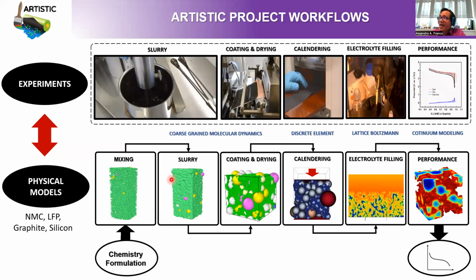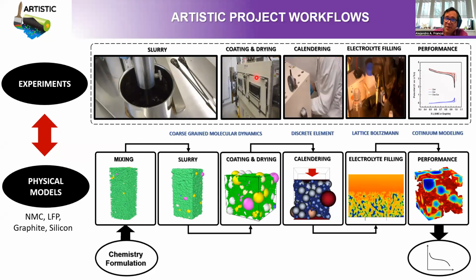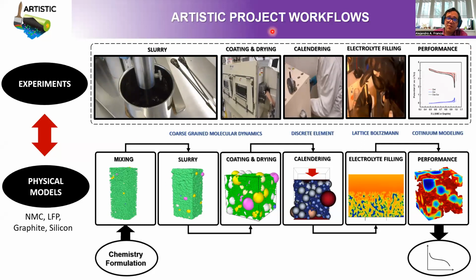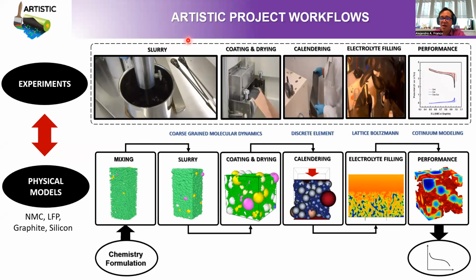So first of all, this is a recap of this ARTISTIC project workflow. So we have on one side experiments going on in our prototyping line, where we perform fabrication of slurries, coating, drying, calendering, and so on and so forth. And then we have all these physics-based models which are sequentially linked. We simulate the mixing, which is something that I didn't talk about today because the paper is still not written, right? Then the output of mixing goes into the slurry model. The slurry output goes into the coating drying model. Then the output of this model goes as an input of the calendering model. The output of the calendering goes into the electrolyte model. And the output of the electrolyte model goes as an input of the performance model, right? We have this workflow sequentially coupling all these physics-based models, which are all 3D resolved, describing each step of the